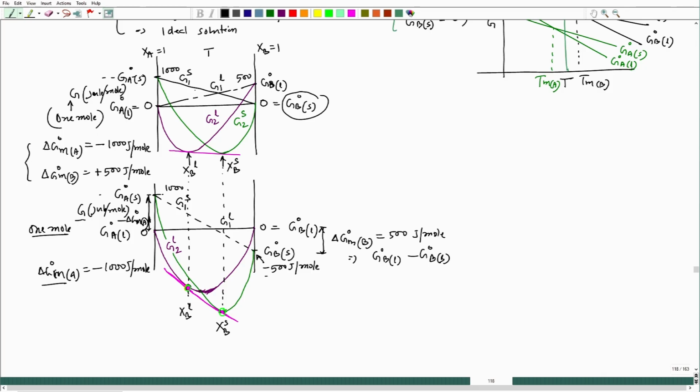Now, you see, even if I change the standard reference value for the pure condition, I will get the same compositions at the same temperature which will be under equilibrium. So, this is another important aspect: what reference value you are taking would not matter, because finally, we are actually dealing with the free energy difference.